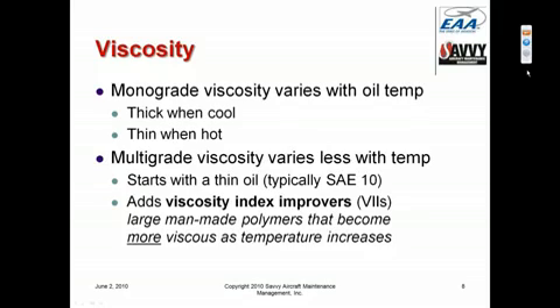To make a multigrade oil, you normally start with a thin, non-viscous oil, typically something like SAE 10 or SAE 15 oil, and then you add a viscosity index improver, which is an additive. It's a man-made polymer that has the very unusual property of getting thicker as it heats up rather than thinner. So the base oil thins out as it heats up. The VI improver gets more viscous and thicker as it heats up. And so by blending in the appropriate amount of VI improver, the oil manufacturer can make the viscosity versus temperature curve pretty much anything he wants.